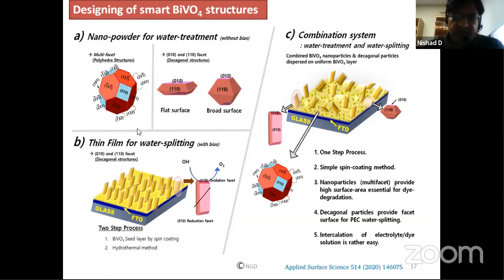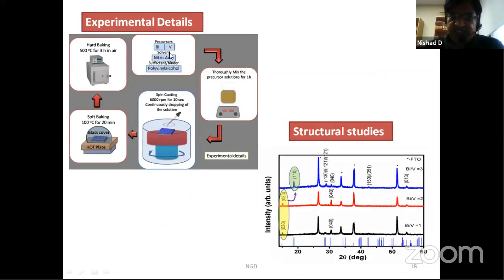Here, this is our experimental details where you can see that simple bismuth vanadate precursors were mixed into nitric acid, and then they were mixed thoroughly and spin coated on FTO substrates. And after annealing, you can see that the structural properties are shown here. So we changed the bismuth and vanadate concentrations, and what you can see is the 002 facet is changing towards 111. So that means you can now control these facets with just changing the concentrations.